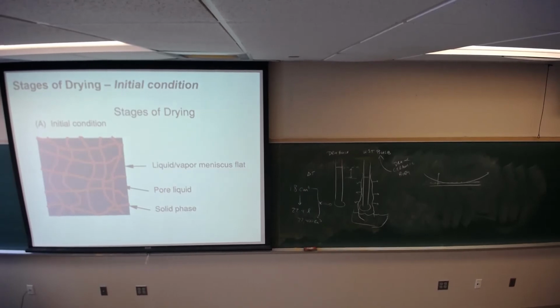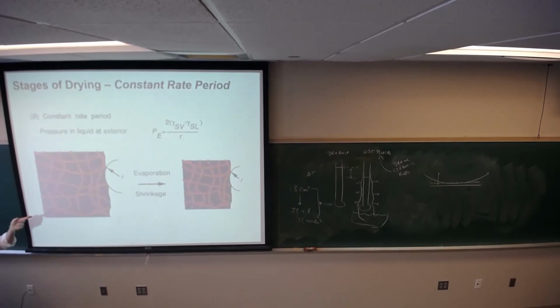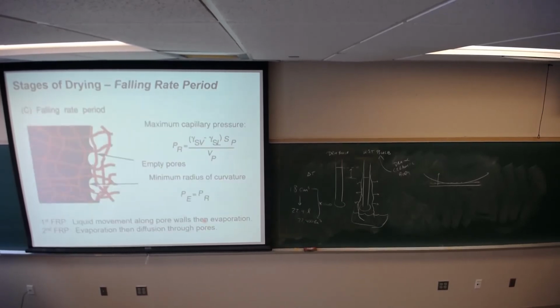George Scherer developed this model. This is the micromechanical model. He developed this network. It's assumed to flatten the meniscus when you start, and as soon as you start to evaporate water, you get a curvature of that meniscus, a radius of curvature, and then he calculates a bunch of stresses associated with it. And then the argument is that I have this constant rate period on the left, okay, and the idea is I'm shrinking the body, but my evaporation rate stays the same, okay, and then in the next step, he says, well, it starts to move into the body, but typically this network will get shrunk,